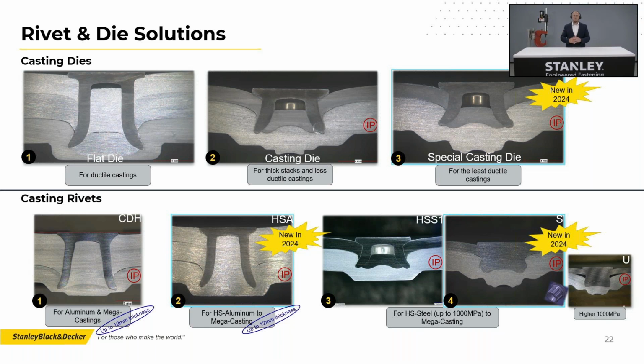And then the newest development, the fancy geometry that you can see on the right, on the top, that's the special casting die, and that's a mixture of the casting die and some improvements to really support the material flow and to be sure that we have a really low risk or no risk to get any cracks with F-temper. That's what I talk about the most when I talk about these castings, F-temper castings, mega castings. Then we have new rivets. The first one is the CDR. Actually, it's not that new. We already had that since a few years,